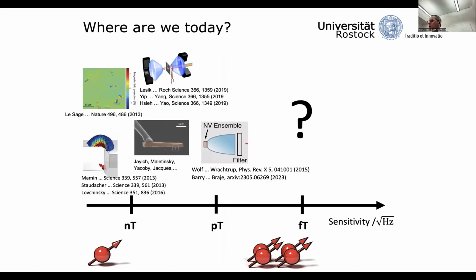However, if we look at the success stories of the past 2 decades, then it's quite striking that all these nanoscale dreams have pretty much become reality. We have seen atomic force microscopes using single NV centers as a smart magnetic field scanning probe. We have seen single molecule NMR being realized by NV centers. We have seen imaging at the microscale. We have even seen these experiments being performed in very exotic conditions like diamond anvil cells and enormous pressures.